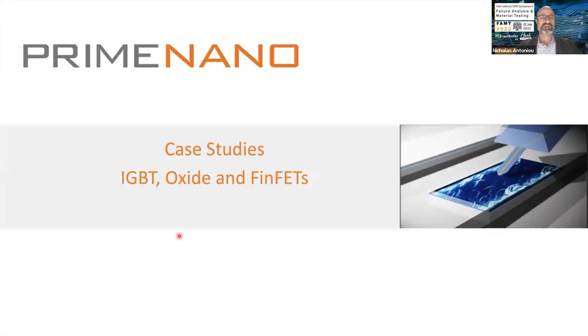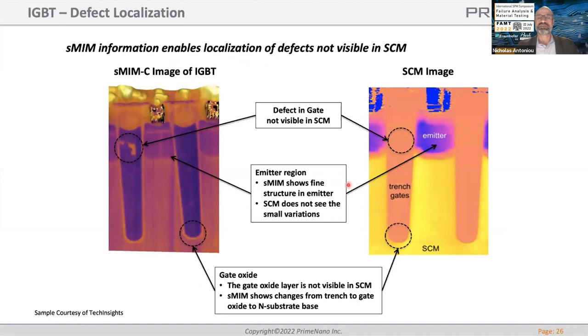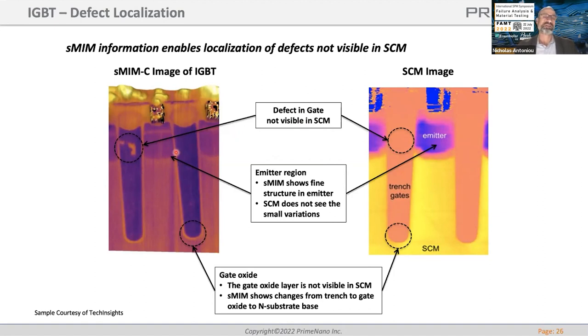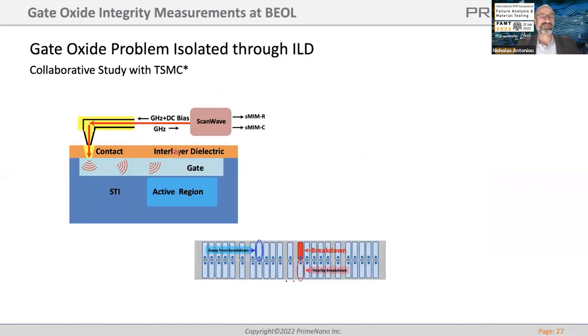Now some additional case studies: an insulated gate bipolar transistor where scanning capacitance was used to look for defects, but the amount of information the microwaves provide is significantly higher. You can very clearly see the gate oxide around the trenched gate, tell the dopant level differences, and there is a defect here that was not visible in scanning capacitance. This shows the great detail that scanning microwave impedance microscopy provides. This sample is courtesy of TechInsights, as was the image sensor.